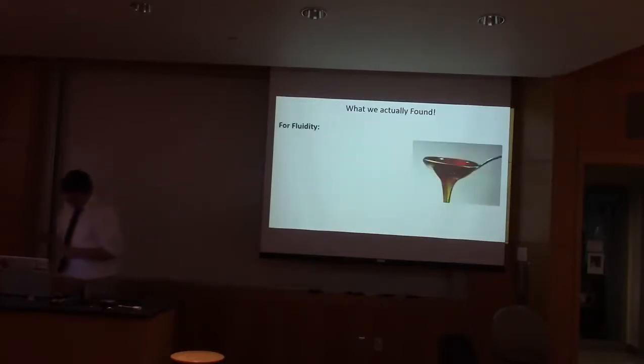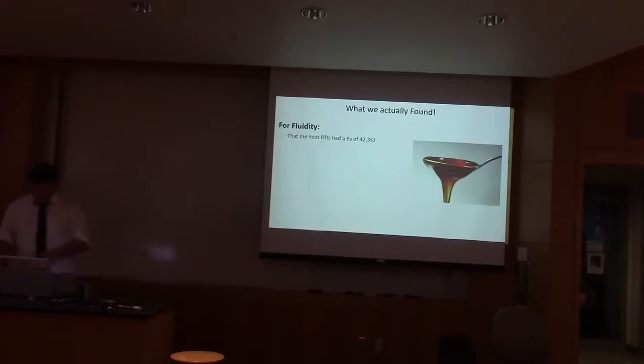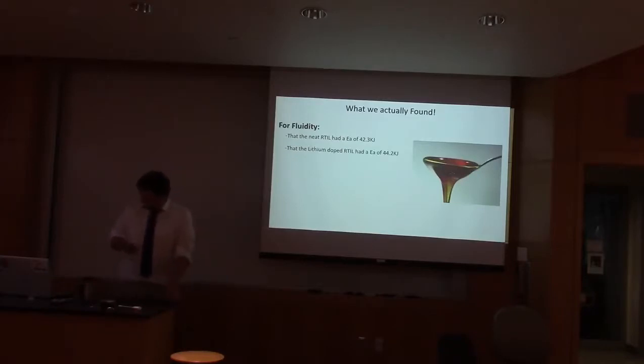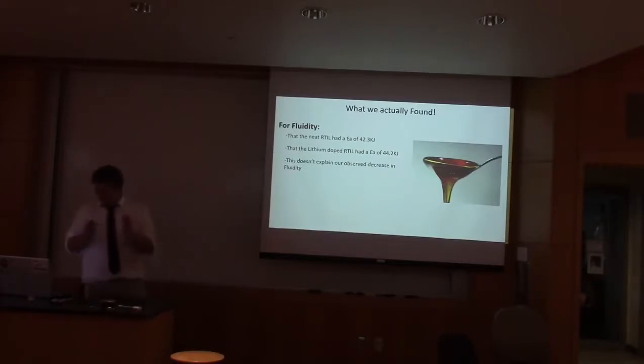What we actually found. For fluidity, which is the data we do have, the neat RTIL, so basically the non-lithium room temperature ionic liquid, had an activation energy of 42.3 kilojoules. In comparison, the lithium-doped room temperature ionic liquid had an EA of 44.2. This is not significant, that's not very different, and does not necessarily explain why we see a dramatic shift in conductivity and viscosity, or in this case, fluidity, for our room temperature ionic liquids between the lithium and non-lithium samples.